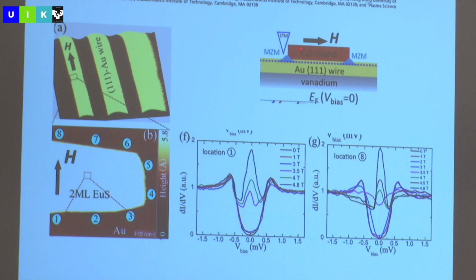And the claim in this paper was that at the exact interface where superconductivity and ferromagnetism, proximitized through the gold in this case, met, there were these striking Majorana peaks if you looked at the right place. And this was just an island of europium sulfide. Here's the island. They applied an external magnetic field to magnetize it, and they saw these zero bias peaks. So it's already kind of coming into topology that you might be able to use this. I think it's the first experiment after this theoretical proposal. I would say a little bit of a clunky geometry, but first experiment out of the blocks was claiming to see these zero bias peaks in the vicinity of the interface between the europium sulfide and the proximitized gold underneath it.